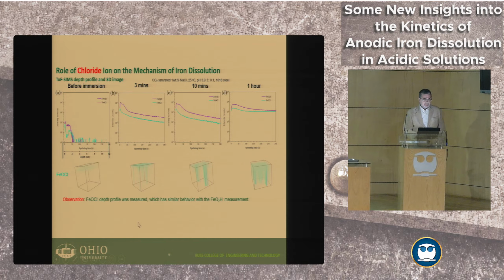So here the blue is this profile of this FeOCl minus, which is some sort of an indication of a chloride compound on the surface. And if you look at it, basically nothing to start with, and then it starts developing, and you have these localized chloride contents as you go deep. So chloride doesn't cover the whole surface, but it forms like islands. So if you want, like pits, but you have to remember this is only a nanometer across, so whether you want to call it a pit. And in the end, after 1 hour, lots of these chlorides as part of the surface.